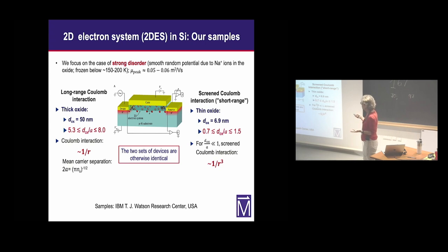They both have a strong disorder, as you can see by this very, very low mobility. So the difference is in the thickness of the oxide. In the so-called thick oxide samples, the Coulomb interaction is 1/r. And in the case of thin oxide samples at low enough densities, it assumes a dipolar form. Now, importantly, these two sets of devices were fabricated simultaneously. There are more than 100 steps in this fabrication process. They were all identical. The only difference is in the thickness of the oxide. So if there is any difference in the behavior of these two systems, it must be due to the difference in the range of the Coulomb interaction.